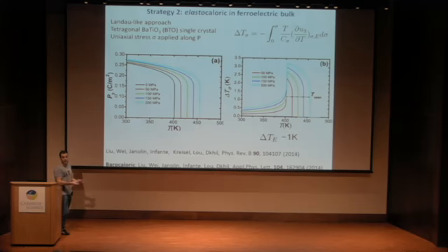So it means that we have a change of the entropy, and associated to this change of the entropy, we have a delta T, which is measured or calculated here. And you see that the values are very close to the one when you apply the electric field. So elastocaloric, in case of ferroelectric, is more or less equivalent, or the amplitude of delta T is more or less equivalent to that of the electrocaloric properties.